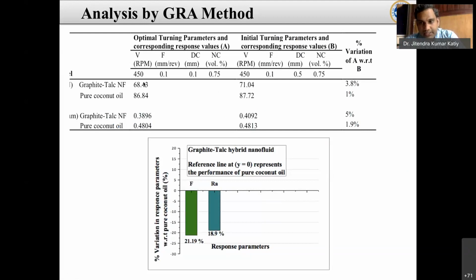There are a total of three cross four, most of them a total of 81 experiments. In between, I checked the confirmation test with the graphite talc nanofluid and pure coconut oil. You can see this optimum parameter: the forces are 68.6 and 86. So that is good.